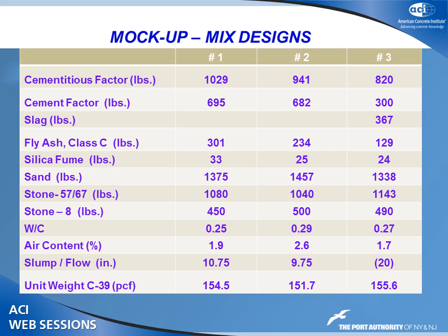That's certainly mass concrete. And if you put together concrete that has a high cement factor, you're going to cook a lot of that concrete. There's no question about it. So we said, you're going to demonstrate to us that you can get this 160 degrees in a block of concrete. So anyway, I'm going to show you some results from this mix here and this one here.